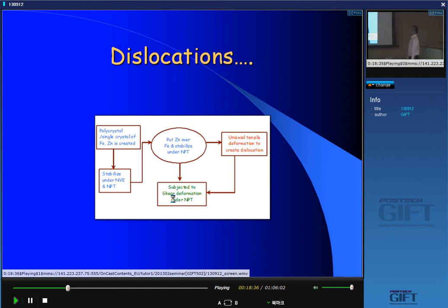Another thing is that although I still call it a toy problem, it is not a real problem because we really do not have that many atoms to represent, say, a piece of steel this big. But still, we want to make it as realistic as possible. I can simulate a zinc coat over a piece of iron on the computer screen. I can create various phases on it. I can shear it, but that's not the end of the story. Normal coated zinc will have the usual defects. It has those dislocations, which we also artificially induce in this system. That means now I am ready with a toy model of a coated steel, which has defects, which has all the phases, which has realistic conditions of shearing and failure.